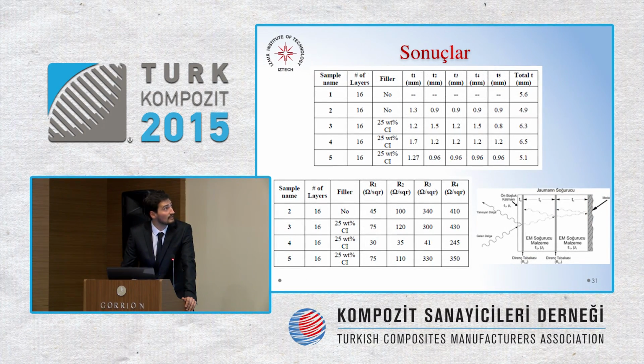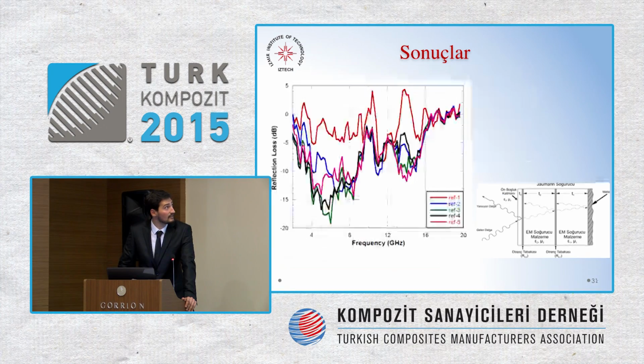But before that, after the first part, we had Mutlu work on that. We increased the number of layers. It was 8 normally, but we increased the number of layers to 16. We use epoxy again. And he adds more resistive layers. I used 3 and he used 4 maximum. And our fillers are the same 25% for both of us. And the modeling is similar.